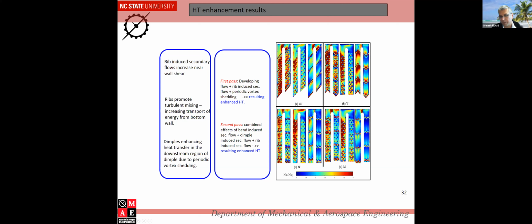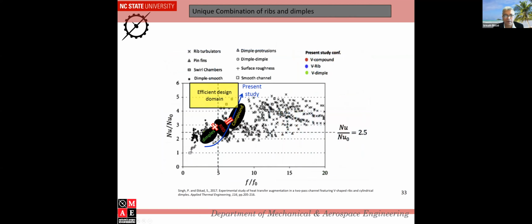So I change the rib to W to see if W helps, and I get the same result. It doesn't matter what kind of rib I use, what kind of dimples I use, I always get higher heat transfer when I combine these two. Dimples cannot be made in conventional manufacturing in a blade, but additive manufacturing can do that. So we were able to take dimples and ribs and move toward the efficient design domain, getting up to 4.5 heat transfer, and pressure drop only went up a little bit. I'm sorry, the ribs should actually be here, but we got a higher heat transfer coefficient.